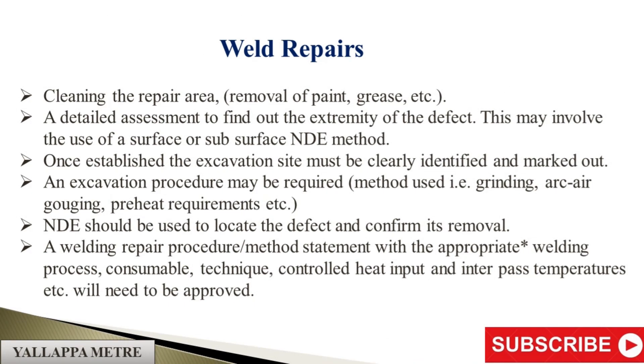Weld Repairs — Cleaning the repair area: removal of paint, grease, etc. A detailed assessment to find out the extremity of the defect. This may involve the use of a surface or subsurface NDE method. Once established, the excavation site must be clearly identified and marked out. An excavation procedure may be required, specifying the method used — that is, grinding, arc air gouging — and preheat requirements, etc.